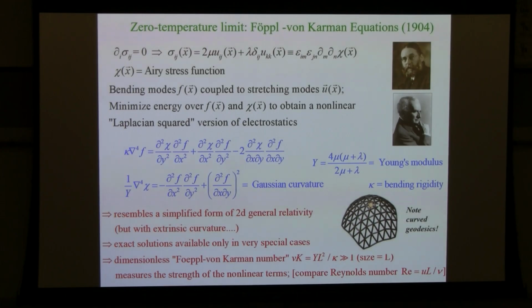This is a 5-fold disclination in a triangular lattice. When it gets big enough, it looks like a cone. And in this cone solution, you notice that at this point of 5-fold symmetry, a concentration of Gaussian curvature acting as a source on chi produces these curved lattice lines, which are basically curved geodesics. So these geodesics bend in the vicinity of this Gaussian curvature singularity. And I'll show you in the next slide.